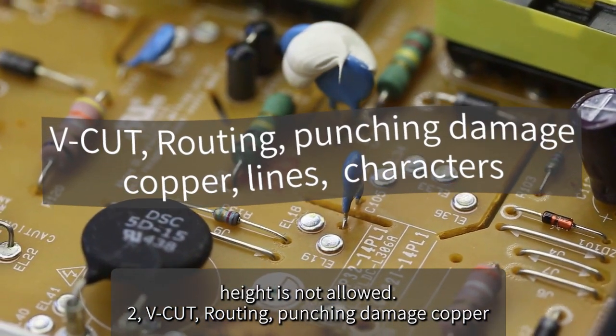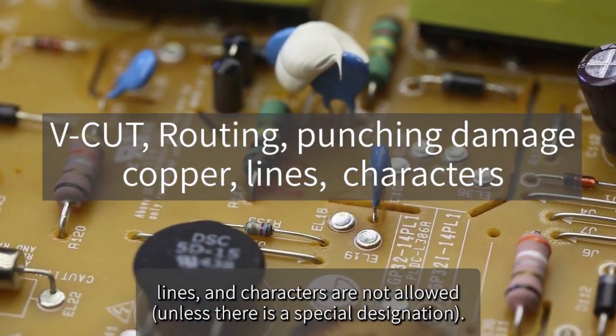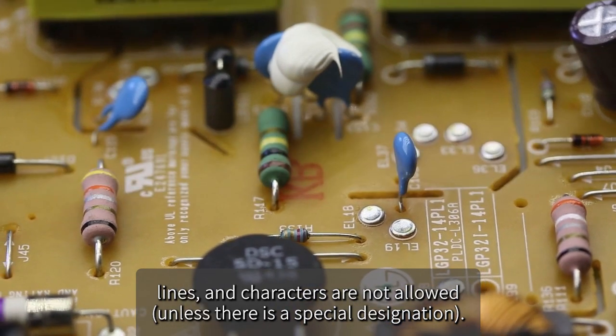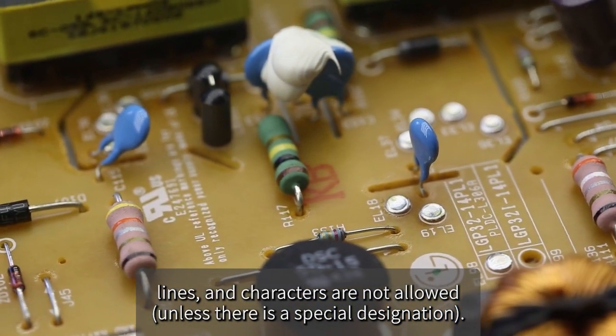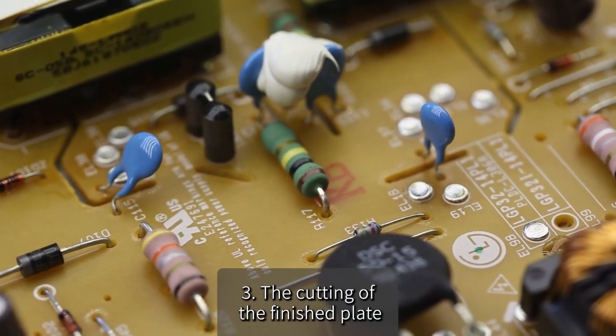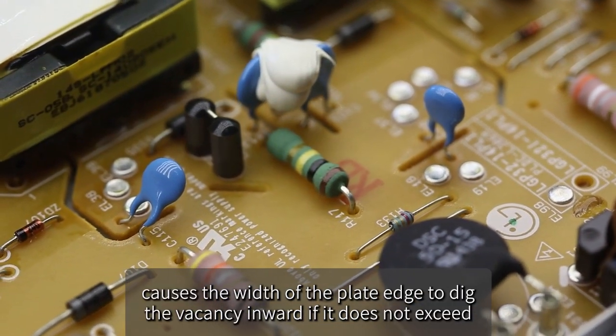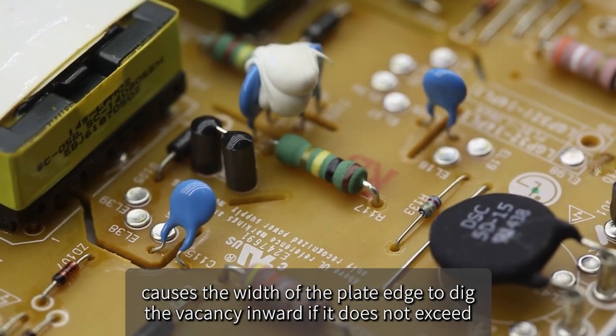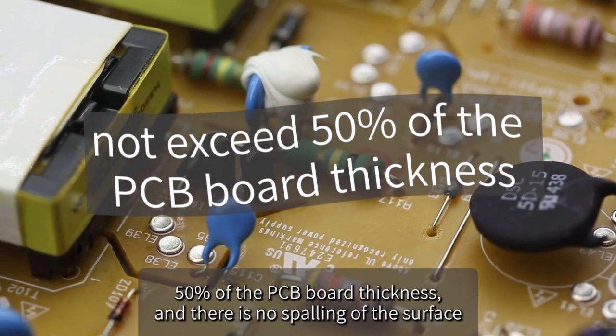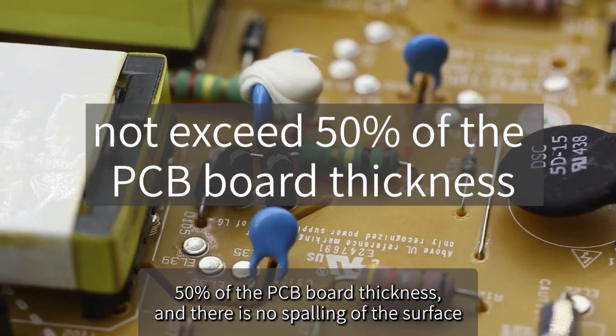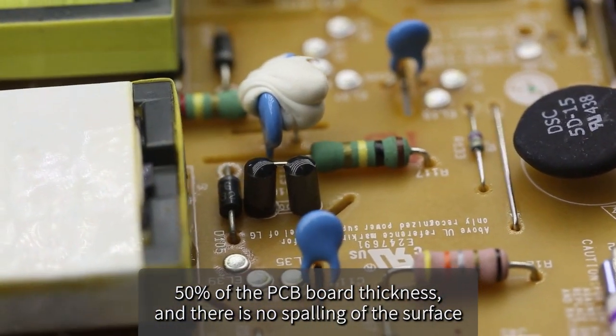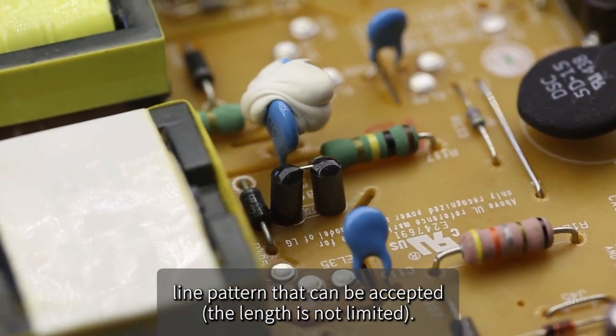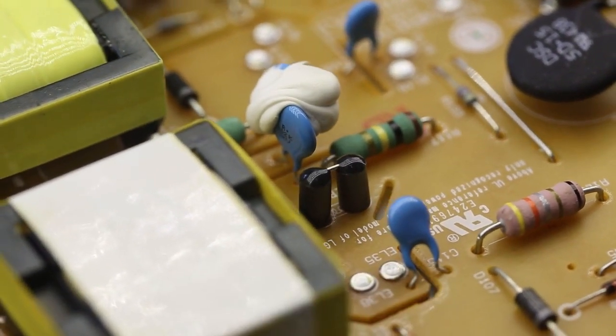2. V-cut, routing, punching damaged copper, lines, and characters are not allowed, unless there is a special designation. 3. If the cutting of the finished plate digs a vacancy inward on the plate edge that does not exceed 50% of the PCB board thickness, and there is no spalling of the surface line pattern, it can be accepted. The length is not limited.